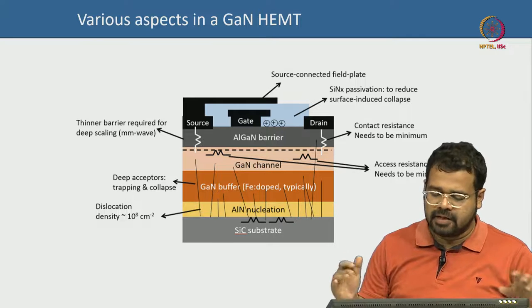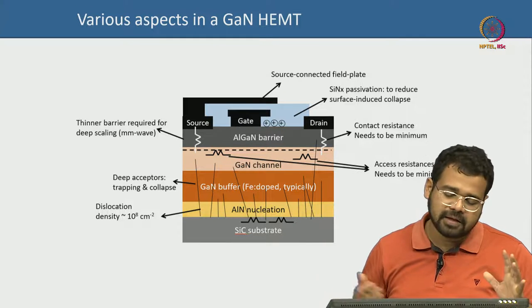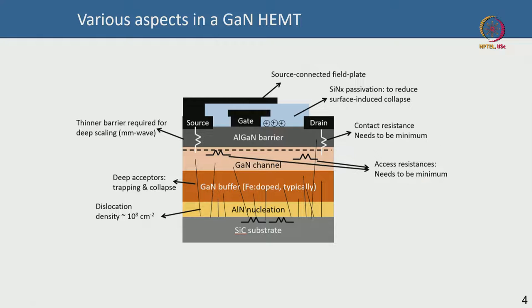This summary slide covers device aspects to keep in mind for gallium nitride HEMT RF applications, especially power amplifiers. Most GaN RF devices are fabricated on silicon carbide substrate, which gives excellent heat management. The lattice mismatch of GaN with SiC is relatively less than with other substrates, giving relatively better crystal quality than GaN grown on silicon.